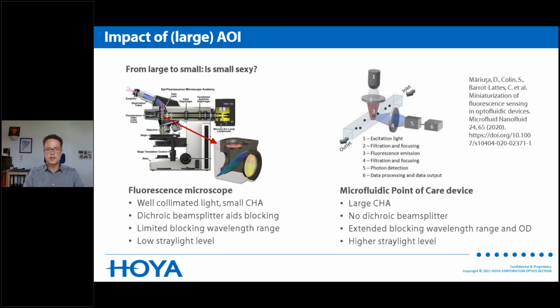What we recently see is that the same fluorescence technology is used in smaller instruments, point of care devices. That has been especially fueled by the corona pandemic for corona quick testing instruments. And in these miniaturized compact instruments, you have large cone half angles. You can't use a dichroic beam splitter. And because you have a silicon-based detector, you need an extended wavelength range. And because the beam splitter is missing, you need a higher OD value in the excitation and emission filters. And because of the compact design, it's not very easy to control the stray light level.